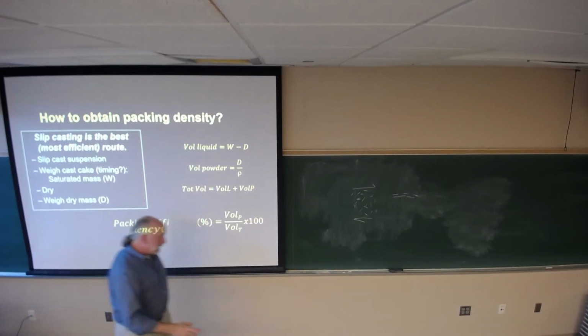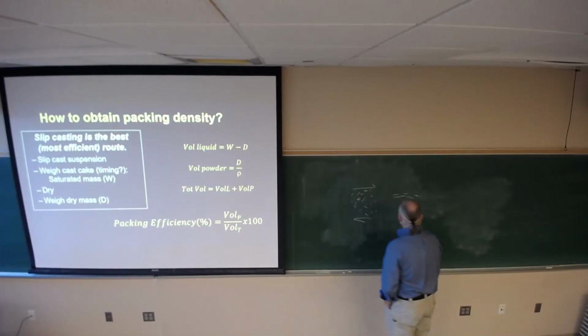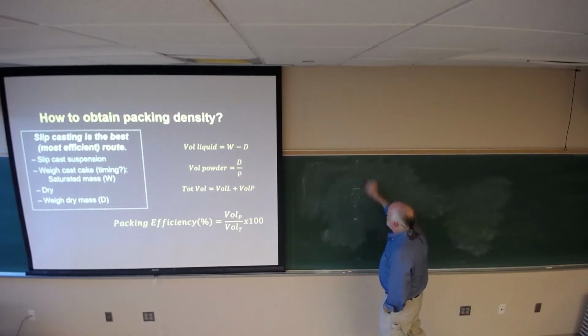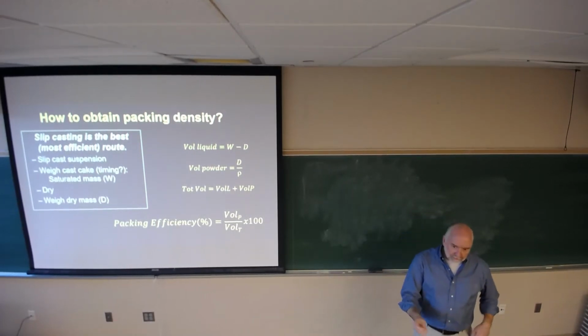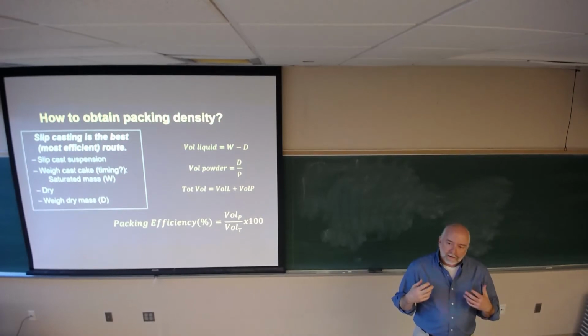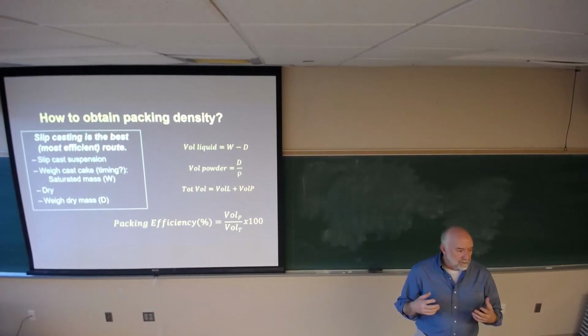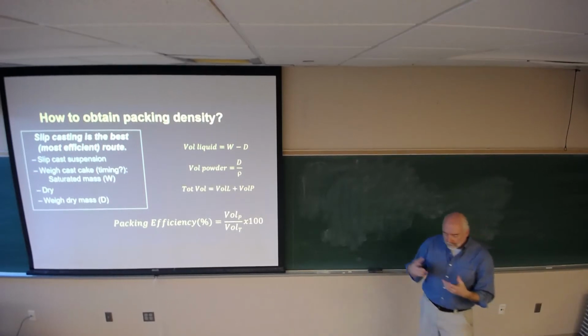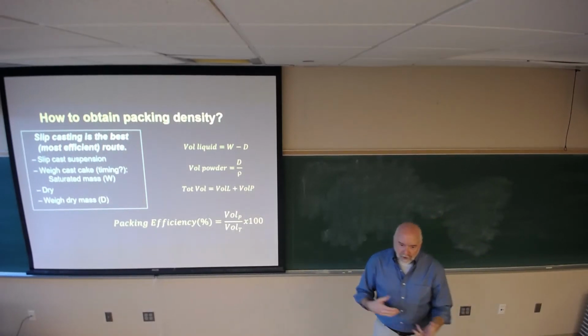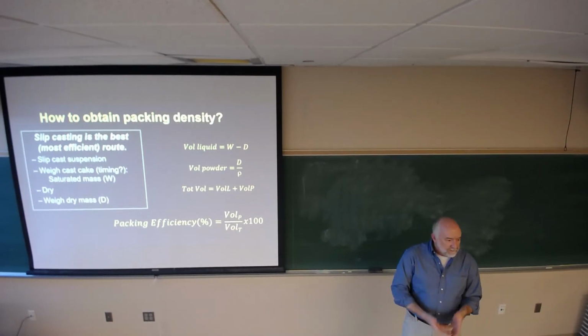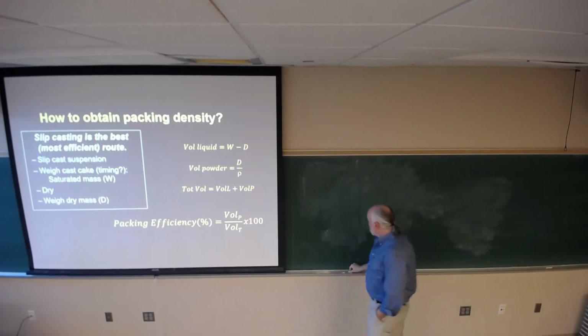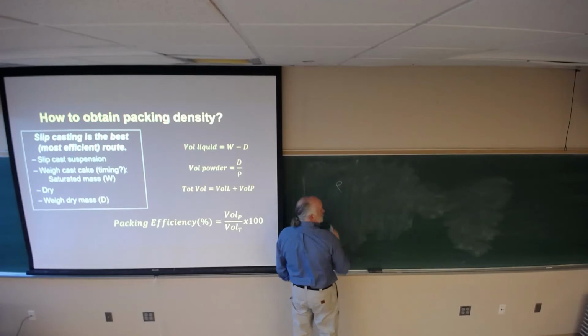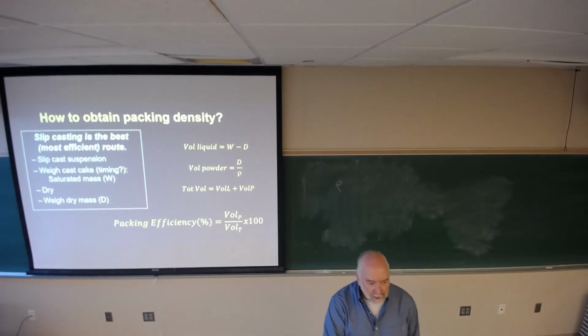Nestor, the guy who did pressure casting, came into my office and we were talking about the density of the system. The way we used to do it, you would take a slip cast body and dry the body, and then introduce kerosene to fill the pores. You would saturate the pores by vacuum, do the dry weight, the saturated weight with kerosene, then suspend it in kerosene to get a kerosene displacement. So your typical density through immersion, and I encourage you strongly to call it immersion, not Archimedes.